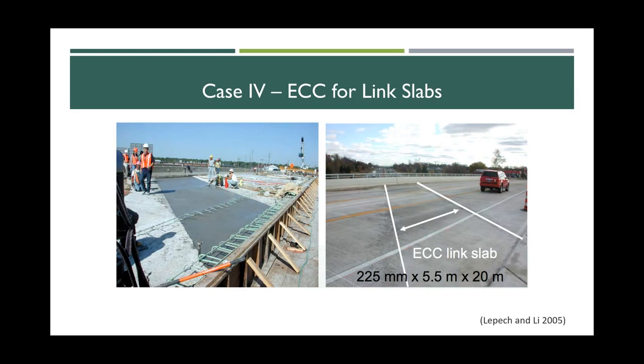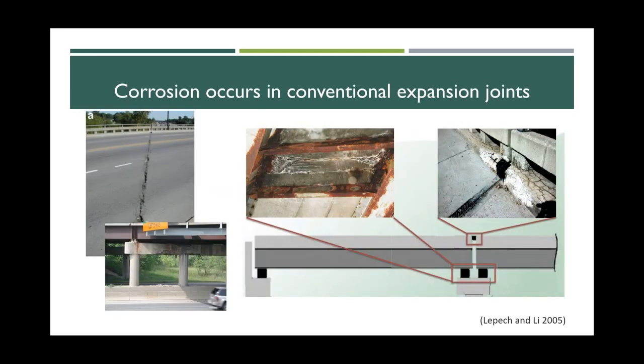And the final case is ECC link slab. Why do I talk about link slab? Because when we build constructions, we cannot build a very long bridge. We have to build segment by segment. And in order to build segment by segment, the conventional way is to have an expansion joint. You can see it here, and you can see expansion joints everywhere. If you drive from here downtown to the airport, you see a lot of bridges overhead with expansion joints, and you can see from underneath that all the steel supporting areas are corroded because the water and everything goes through those cracks.